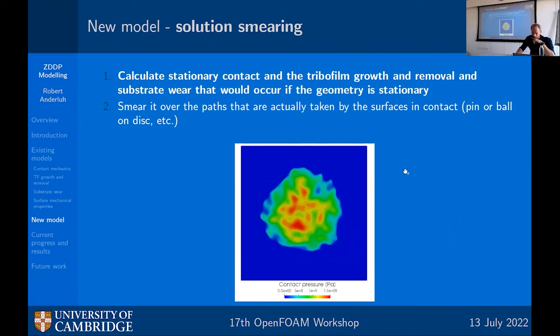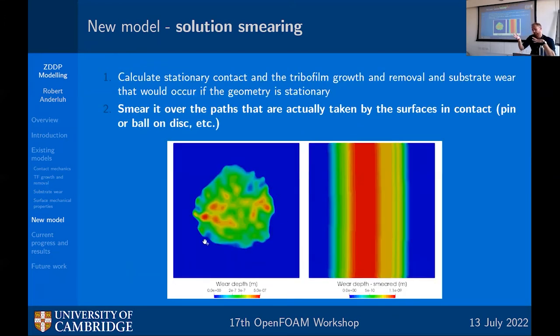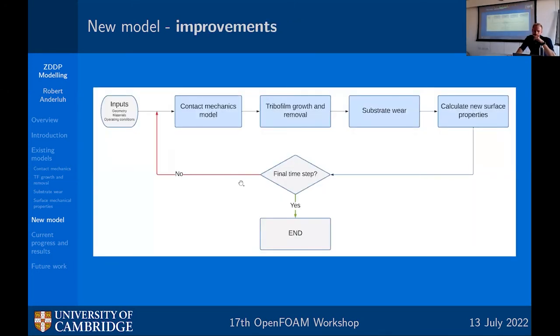And I'm doing something similar, although slightly different, because of the exponential nature of the dependence of tribofilm growth. It is not as simple as that, because what I'm doing is using the contact pressure. So here you see an example of a rough surface simulation and a resulting contact pressure. Then from that, if I'm interested in the wear depth in a given time step, I calculate it as if it was stationary, and then I smear that over. It would be fine if I smeared the contact pressure and then calculated the wear depth from that, but I would have problems with tribofilm growth because it should be exponential, and in that case, it would not be captured. So basically, to reiterate,